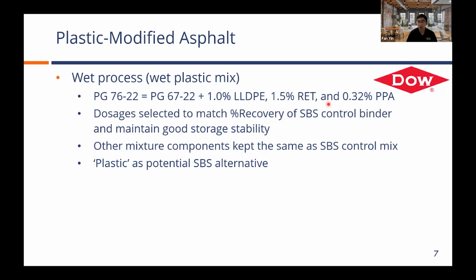We did quite a bit of work up front before we do production, just to make sure we are achieving the engineered property of the binder that we are looking for. In short, what we did was try to match the percent recovery of the SBS binder and also at the same time maintain good storage stability. So we definitely don't want those materials to separate in the tank. That can be a nightmare from the production operation perspective.